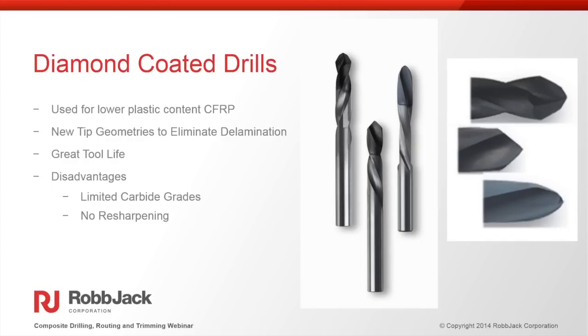When using diamond coated drills, diamond coating is an excellent choice for a drill. And in some applications, you can actually get longer tool life even over PCD drills. Many of the tip geometries that you're able to do on carbide tools, you're able to do for diamond coated, because what we're doing is we're taking a carbide blank, we're leaching out the cobalt at the cutting surface and growing diamond on the cutting edges. So essentially it's a carbide tool that we've grown diamond on the cutting edges to create that diamond coated tool. So you're pretty much limitless on the types of geometries that you could put on there.